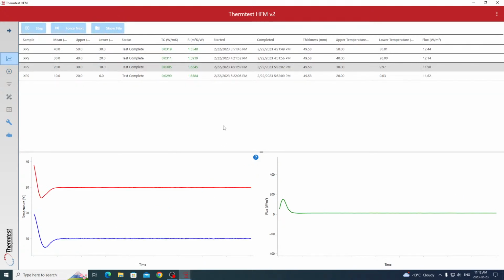So here's measurements done at means of 40, 30, 20, and 10. You can see that here. The upper plate and lower plates have a 20-degree delta. And here are our resistance values and our calculated thermal conductivity values. The 20-degree value is what you'll see spec'd on this material. This XPS is a couple years old, so you would have perhaps some effective degassing, but that's within 5% of the R value reported by the manufacturer. And that is essentially how the HFM-100 and the HFM-50 work.